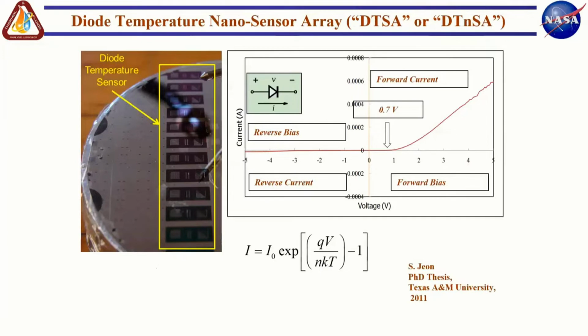And then subsequently, we found that even a 100 nanometer bump on a surface can enhance boiling. So in one sense, these nanothermocouples, which are a 200 nanometer bump on the surface, can actually enhance the boiling. So the act of measurement can enhance boiling. So we were on the lookout for a better heat transfer and temperature measurement platform on the nanoscale.